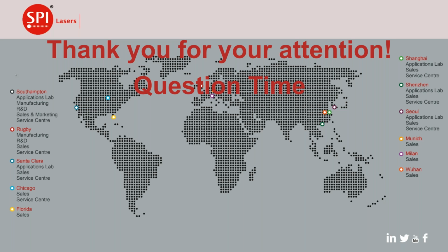And I think finally, just as we're running out of time, there were questions about whether you have to use a single mode laser for oscillation welding. And the answer to that is no. It is possible to use another type of laser. We've looked at using a 50 micron fiber. Again, it has a slightly different profile, but when you focus it down, it gets down to a small enough spot size that the power density can be useful for some applications. And again, it's material dependent.